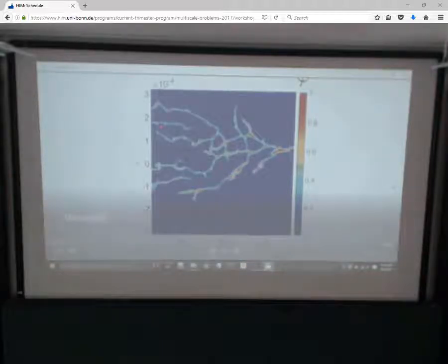And in this case here, this is where the grain boundary is basically half the strength of the grain interior. And so you can actually see some of the grains that are over there. They're forming here. It goes around the grains rather than through them.